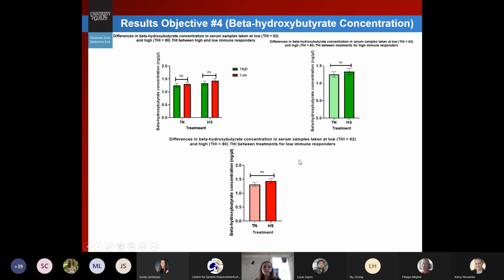And then this slide is showing our results for beta hydroxybutyrate concentration. We didn't see a significant difference between the phenotypes in the thermoneutral or heat stress treatments. And additionally, when looking within phenotype, we also didn't see a significant difference between thermoneutral and heat stress for the highs or the lows. So for this study, we made sure that the cattle were lactating as well as far enough away from calving that they shouldn't have been in a negative energy balance, so that we were just looking at the effect of heat stress itself on beta hydroxybutyrate concentration, and finding that there doesn't seem to be an effect. This actually does correspond with what has been shown in some other studies.